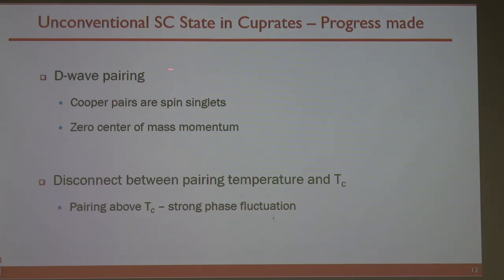I would say for the cuprates, I feel it's pretty solid now to say that it has d-wave pairing. Once you know it has d-wave pairing, you immediately know the answer to this one. Its Cooper pair must be spin singlet. If the orbital is even, then the spin has to be odd. Okay. And to the extent we know, it's a zero center of mass momentum. However, there's another thing about the cuprates which is very unusual, which is the disconnect between the pairing temperature and Tc. These are the two things I'm going to show you with ARPES.